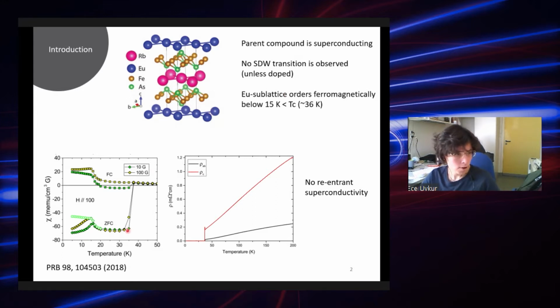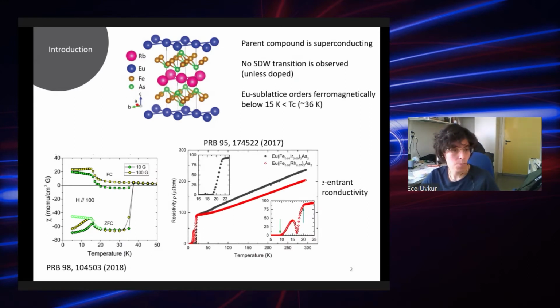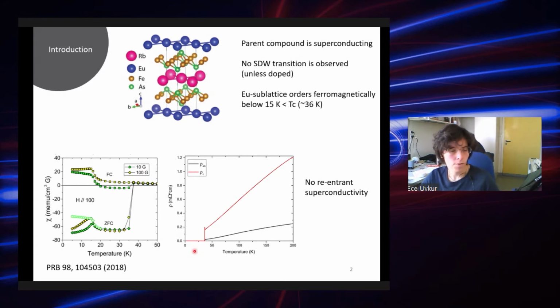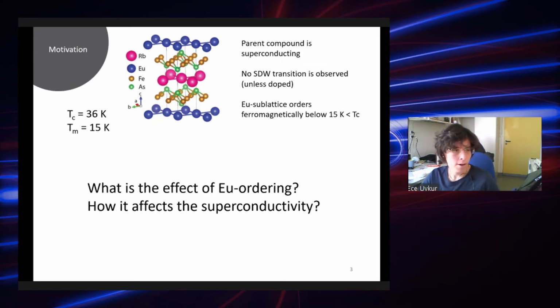So, even though europium orders below 15 Kelvin, in the resistivity there was no re-entrant superconductivity, which was reported for some other iron pnictide superconductors, for instance this rhodium-doped 1-2-2 system here, where you start to see superconductivity appear, but at the ordering temperature of europium it breaks down. This was not the case for this 1144 system, but nonetheless we just wanted to know what is the effect of europium ordering, as it seems to affect quite a lot in other iron pnictide superconductors, and how it actually affects the superconductivity.